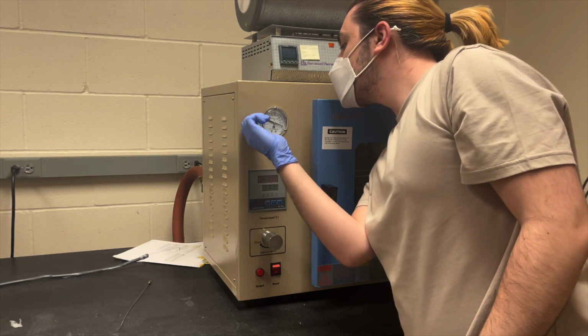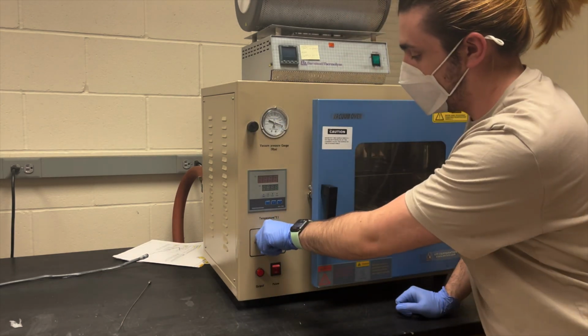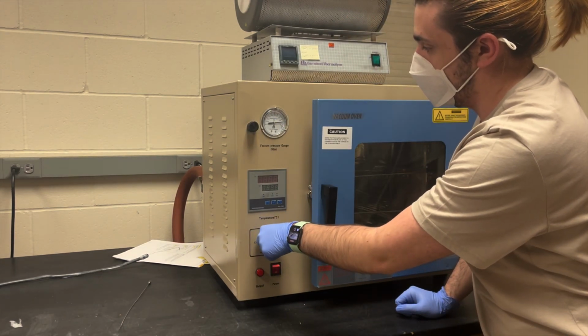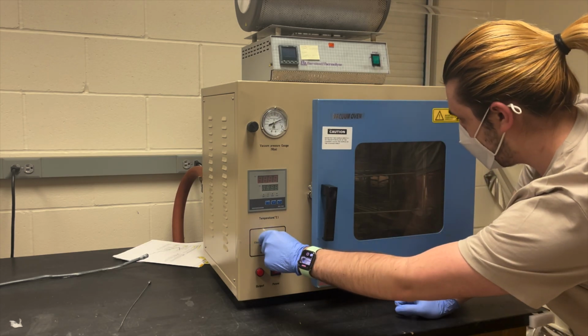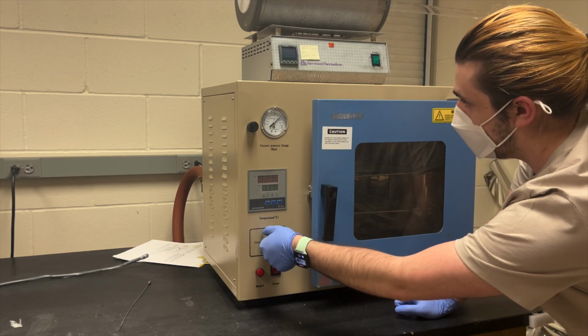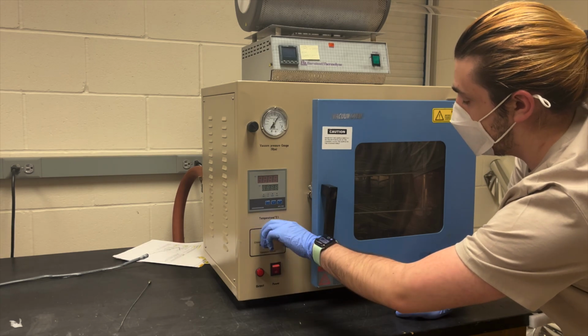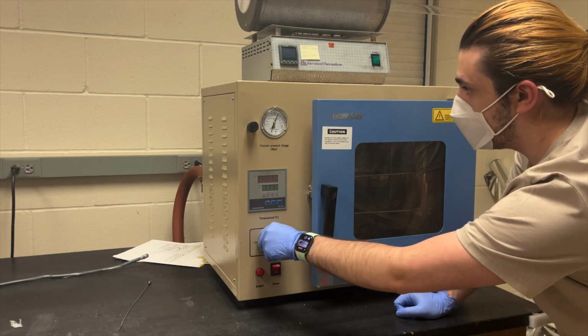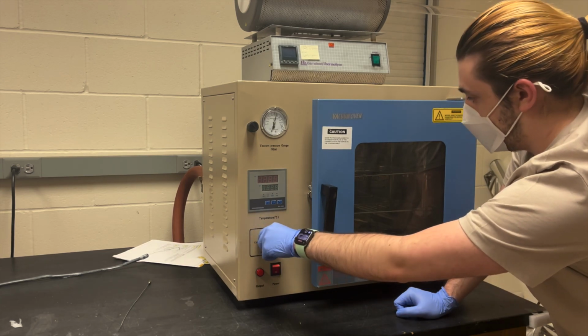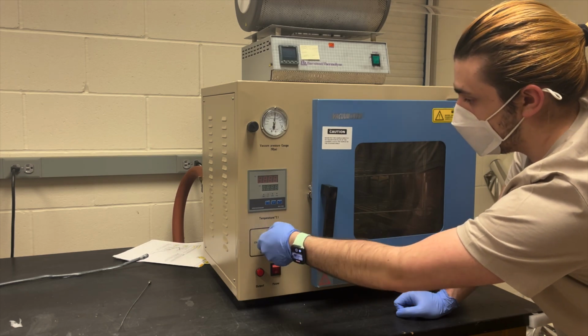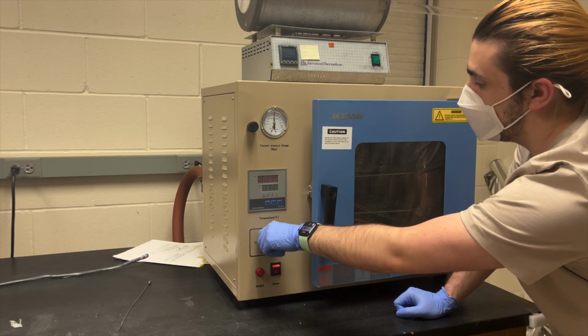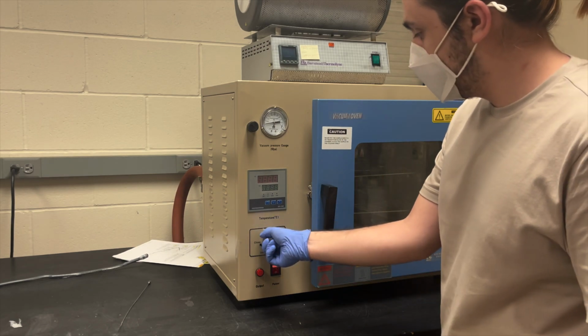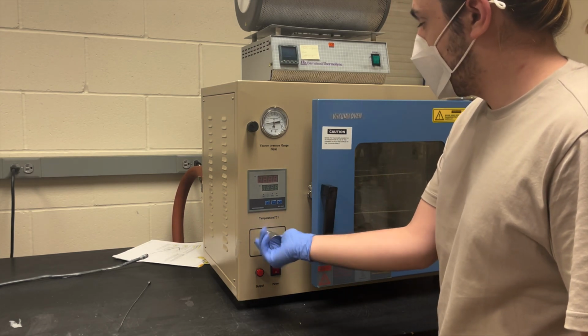I then check the vent valve to ensure it's closed, and then open the valve between the oven and the pump. The needle in the gauge will need to drop below a black dot before closing the valve and turning the pump off. This will take about 10 minutes to occur. Here, I will close the valve and unplug the pump.